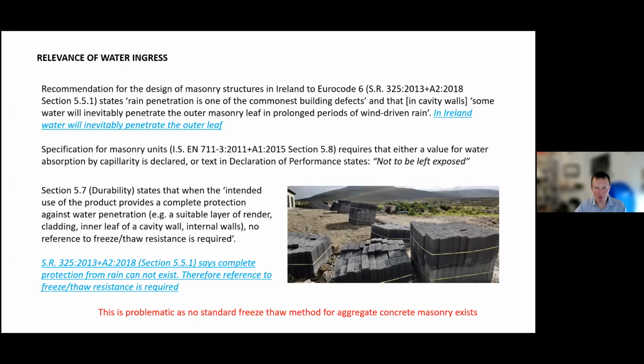And this is obviously a bit of an issue because many manufacturers will leave them exposed in the yard. And also once they leave the manufacturing yard, they'll often sit on building sites wet. So you can see here's a photograph from Mayo, and you can see that the blocks on the top of the bales are saturated and the ones further down are somewhat protected. So we have here a mechanism of how we're potentially altering the concrete before it's built into a wall.